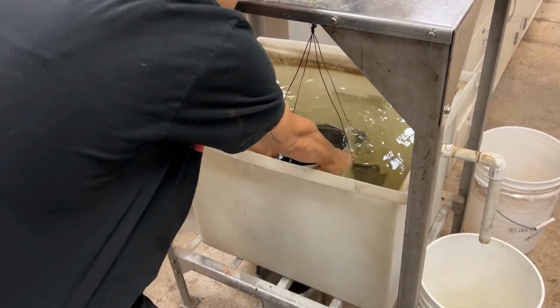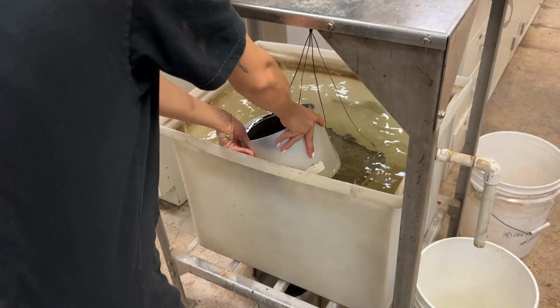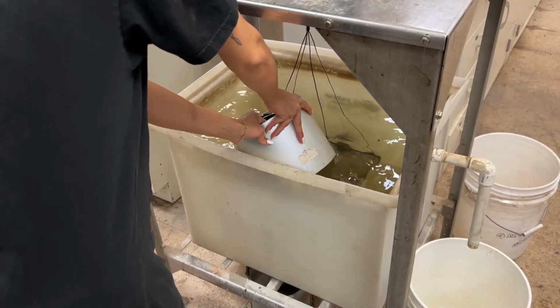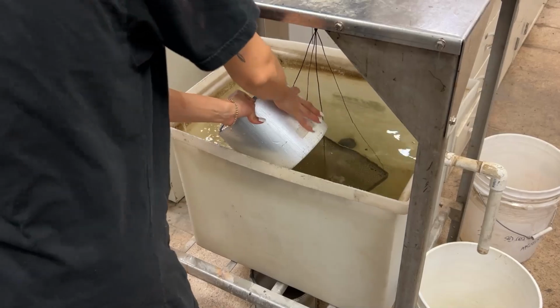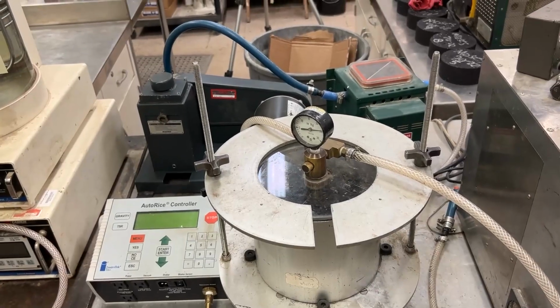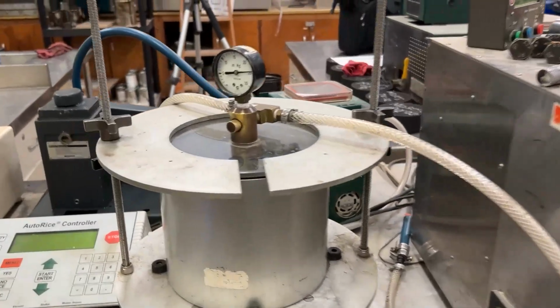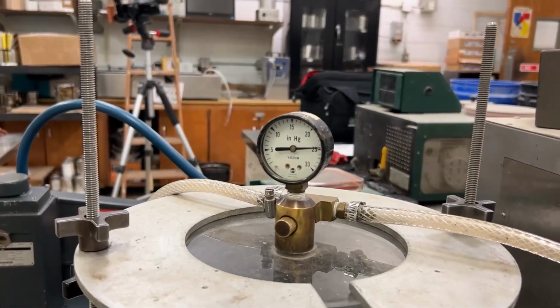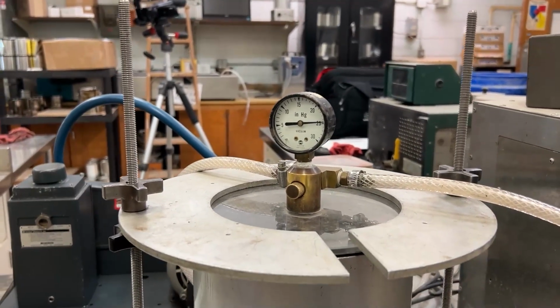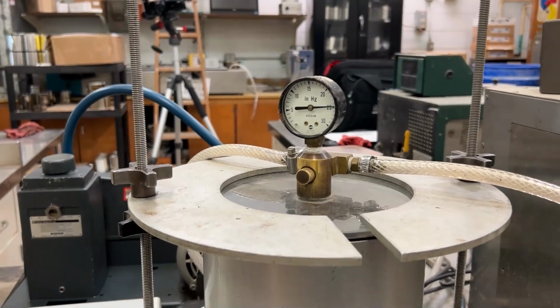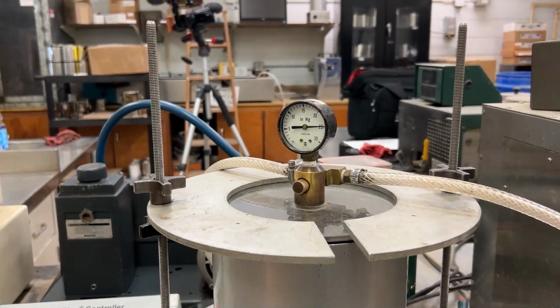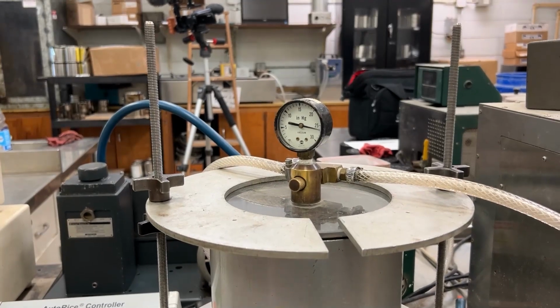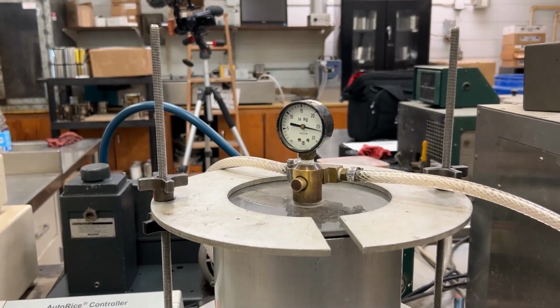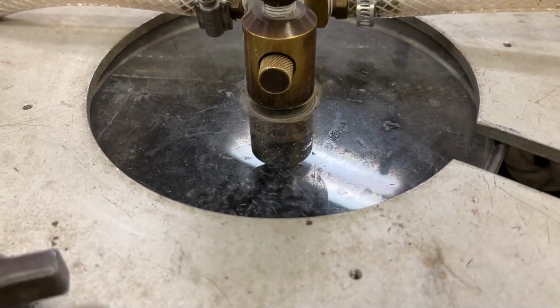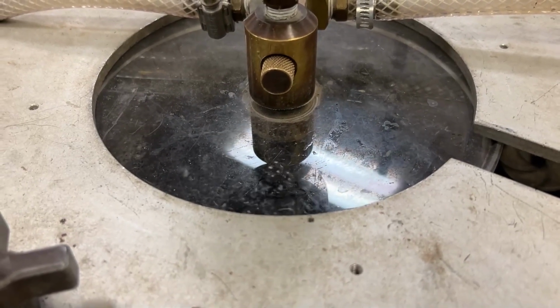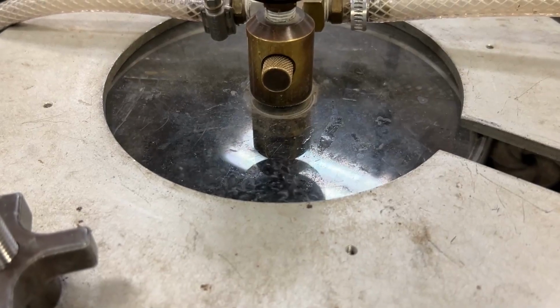A water bath capable of maintaining a uniform temperature to determine the mass in water at 25 plus or minus 1 degree Celsius. A vacuum pump capable of emptying air from the vacuum container to a residual pressure of 3.4 kilopascals or 25 millimeters of mercury. A vacuum gauge to be connected directly to the vacuum vessel and capable of measuring residual pressure down to 3.4 kilopascals or 25 millimeters of mercury or less, preferably to 0.